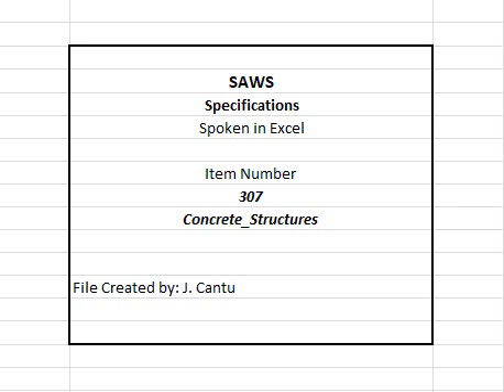A. Form removal from structures shall not begin until the concrete has attained the following compressive strengths. B. Vertical forms shall not be removed until the concrete has set a minimum of 24 hours, or the concrete has attained a minimum compressive strength of 500 psi. C. When wall and top slabs are poured monolithically, wall forms shall not be removed until the concrete has attained a minimum compressive strength of 2000 psi, or as directed by the engineer.